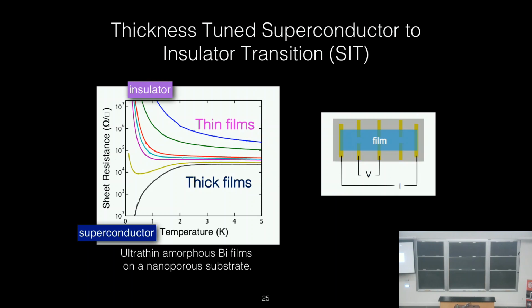So as I said, in the experiment, we can go from thin films to thick films. We did that. We get a nice insulator. Resistance comes down as the film gets thicker. We see this kind of a dip up here. Maybe Cooper pairs are forming and trying to be a superconductor, and we make it a little thicker and we get a superconductor. This is a superconductor insulator transition in these bismuth thin films.